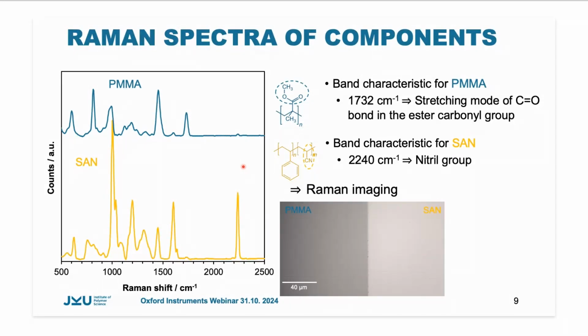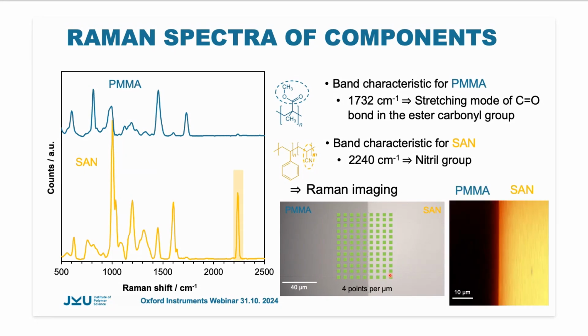Now we can perform Raman imaging line by line, recording Raman spectra. We choose 4 points per 1 micrometer, about 50 to 100 microns in the width, and then also in the second direction, in the line direction, we can choose if we have the same number of lines or not. Nevertheless, after recording the Raman spectra, we have to analyze the data, and therefore we plot a sum filter of the nitrile group and get this image where we see the SAN as the bright domain on the right and the PMMA as dark domain on the left.